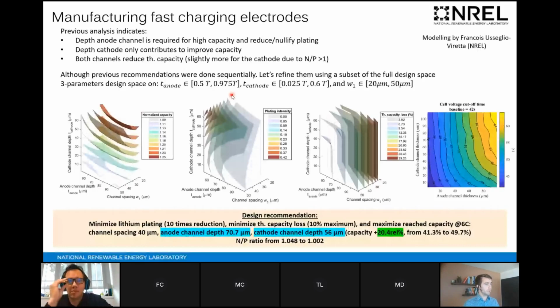So Francois did this very thorough parameter sweep where on the y-axis here we've got cathode channel depth, anode channel depth, and channel spacing, and looked at the interaction of those three parameters on normalized capacity, plating intensity, theoretical capacity loss, and cell voltage cutoff time. That's the time it takes to reach the end of the constant current step of the constant current, constant voltage charging. And Francois found that there's an optimal channel depth of about 70 micrometers in the anode and about 56 micrometers in the cathode.